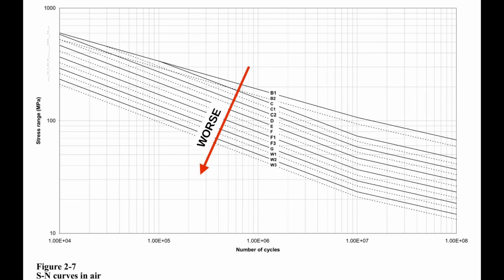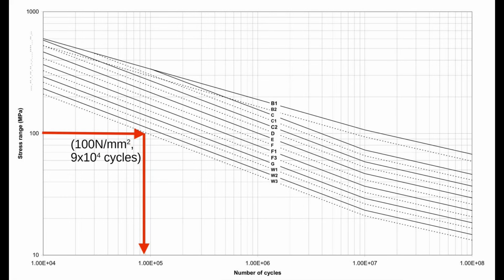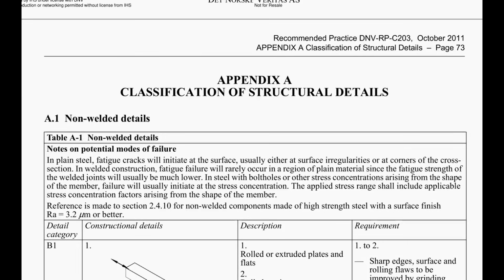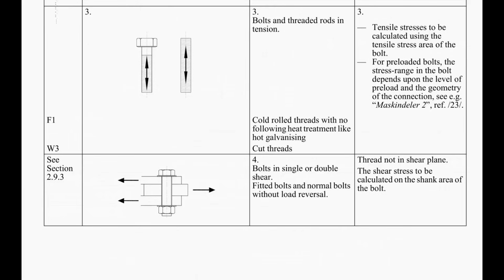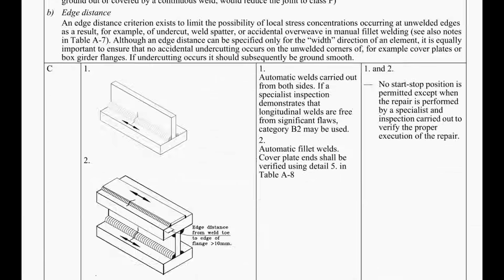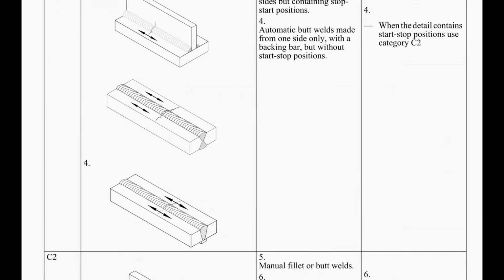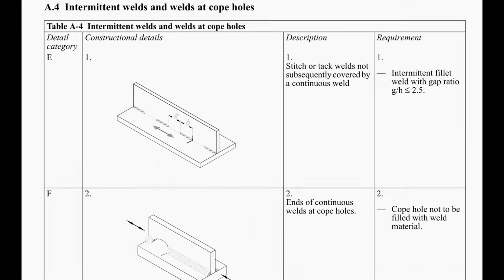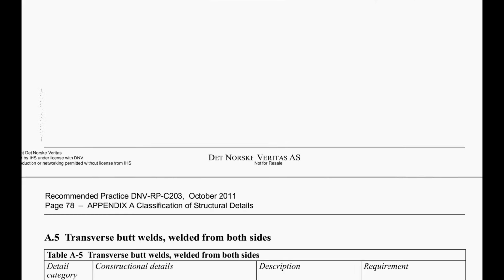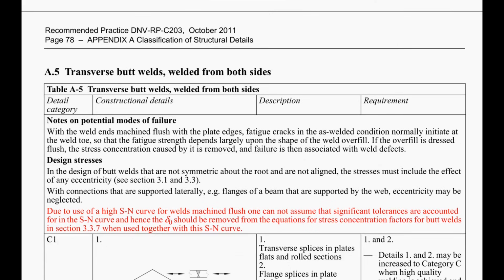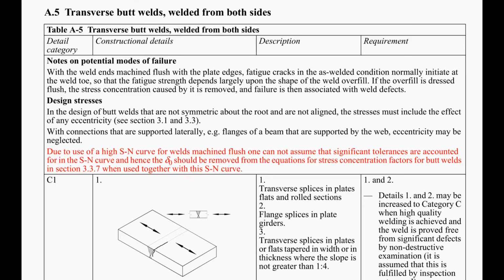But an important point to note is that the scales aren't linear, they're logarithmic, which means that they are highly compressed. So if, for example, we double the stress range to 100 newtons per millimetre squared, we actually find that the fatigue life is only 1/8. Now the selection of the appropriate SN curve depends on the structural detail and the type of loading, and there's a wide range to choose from. However, we are interested in splice welds in chassis members, so I'll be looking at the transverse butt welds.